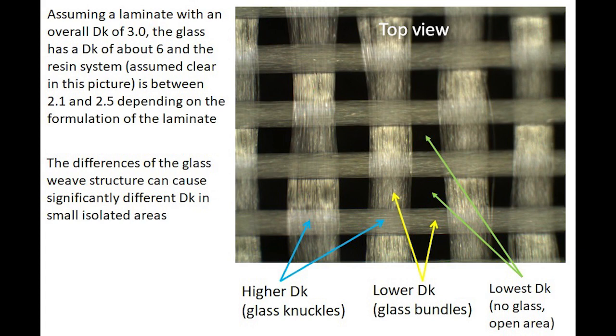And what you can see, if you look at any one of these areas I have pointed out with arrows, is that in the areas with the blue arrows, and specifically where the arrow heads are pointing, that's areas where bundles cross in one direction, bundles in the other direction. So you basically have two layers of glass in that area. In that area, the dielectric constant will be higher because glass has a dielectric constant about 6. And then to the right of that, the yellow arrows, that's pointing to areas where there's glass bundles only and just one layer of glass. So it's going to be a little lower dielectric constant than the glass knuckles.